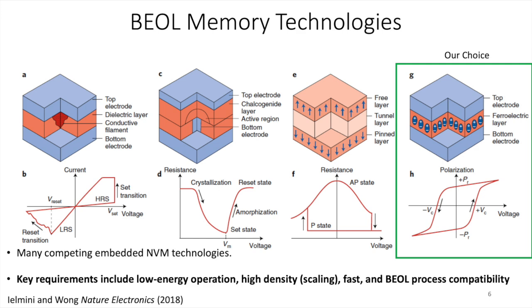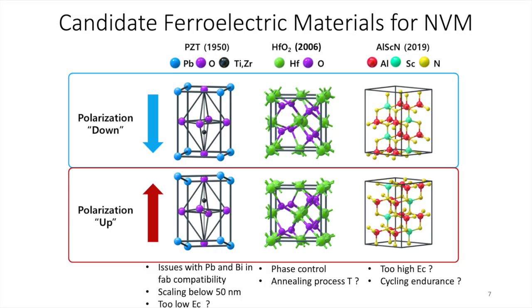Among ferroelectric materials, again, there are many competing materials out there. In fact, back in 2022, which is 2 years ago, the phenomenon of ferroelectricity completed 100 years. So it's more than 100 years since this phenomenon has been known. And PZT, or lead zirconium titanate, is the classical ferroelectric material. People have tried to commercialize it, but it has issues with silicon CMOS fab compatibility.